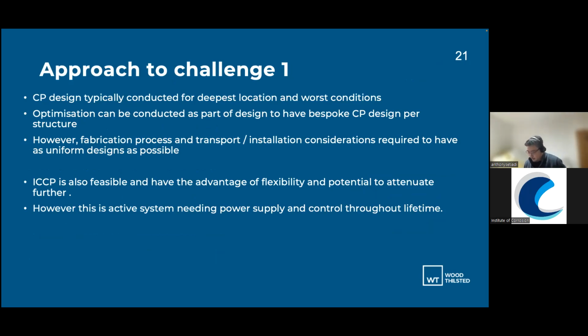So what's our approach? We typically approach by going for the deepest location and the worst conditions. We could try to optimize by having a bespoke CP design per structure, because if we look at a site with a deepest water depth of 30 meters, there can be variation in the water depth down to even 20 meters. So there is between 10 and 15 meter variation in terms of the structures that we are going to see. So we do cluster them for structural design, but for CP design, because of the fabrication process and installation process, we do try to streamline that to make sure they are essentially very similar, and therefore we limit the amount of mistakes that we can make. So that's the balance that we have to give when we're trying to design, and that's why for the moment we design to the deepest, and then we apply that across the board.